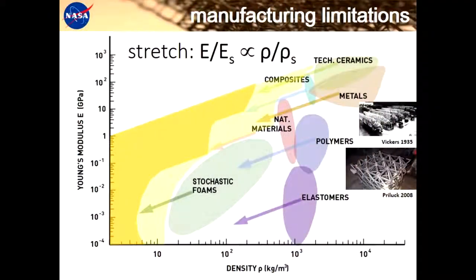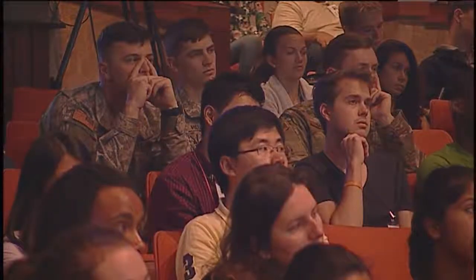So we've had reasonable success getting down to around 1/10 the volume of the materials that you see here, most of them, before reaching the limits of conventional manufacturing methods. So of the designs that are truly volumetric periodic structures, a pioneer of lattice-based metallic structures, Hayden Wadley, has said that it is not trivial to ensure that the increased cost of periodic cellular manufacturing processes is compensated for by the reduction in weight. So whatever cost gains you get in your application through the reduction in weight.